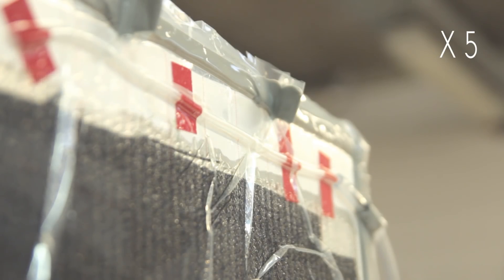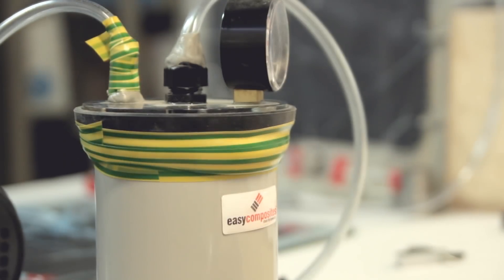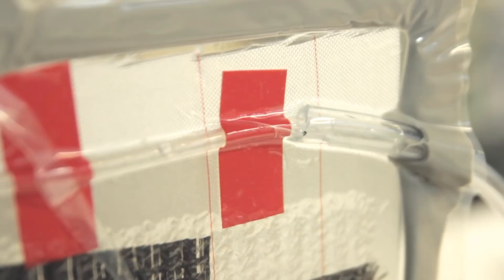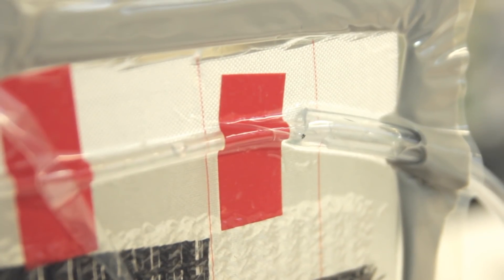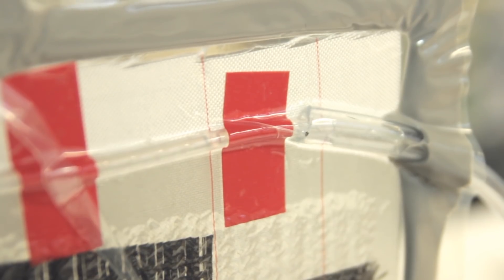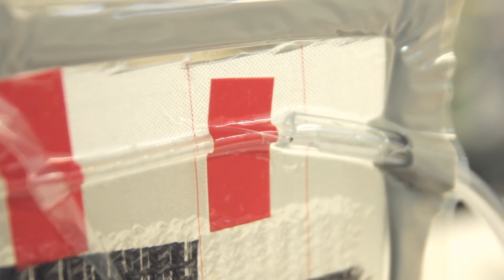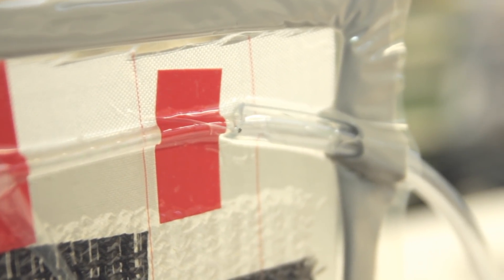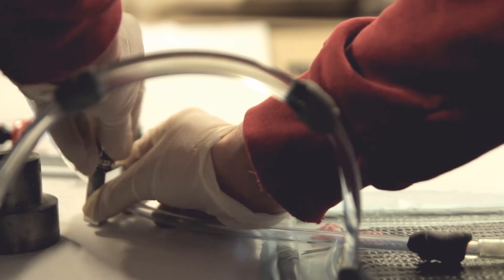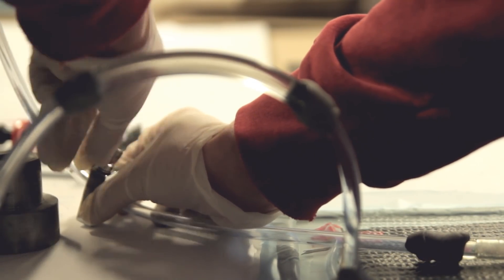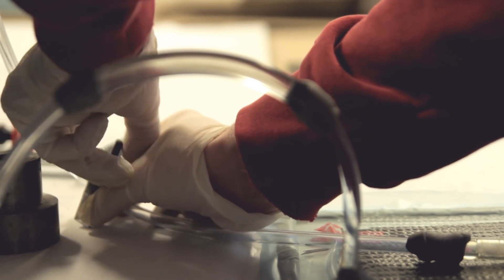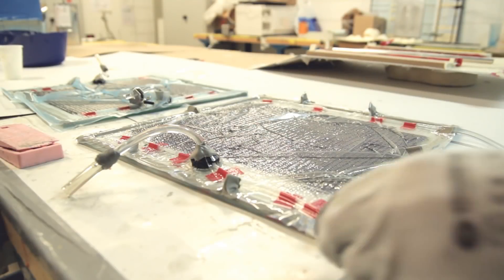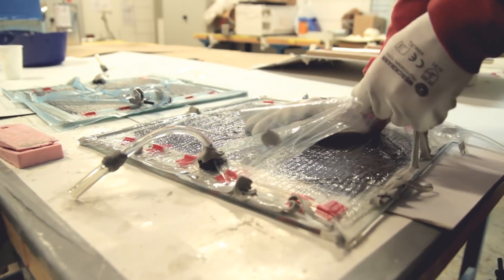Here we are running at the end of the infusion. Everything went well. This is a line going to the catch pot, so resin will flow out into the catch pot if needed. I was able to clamp it off before. Because the resin was degassed in the beginning, you can see there are like no bubbles. You see one bubble - it's really not much. You can do this with a catch pot and just degas everything.